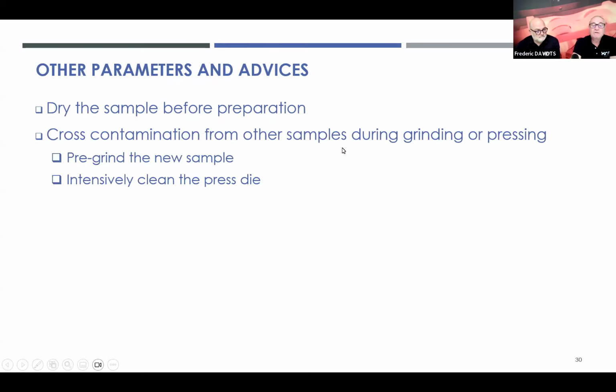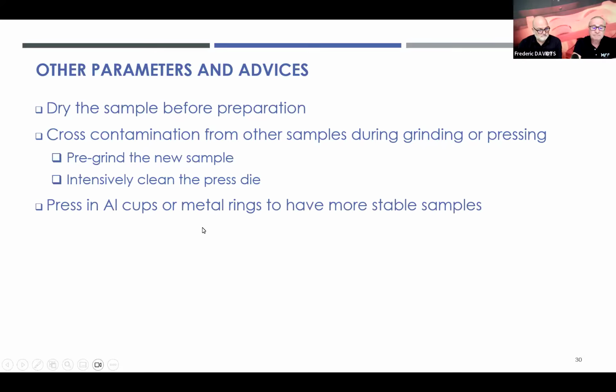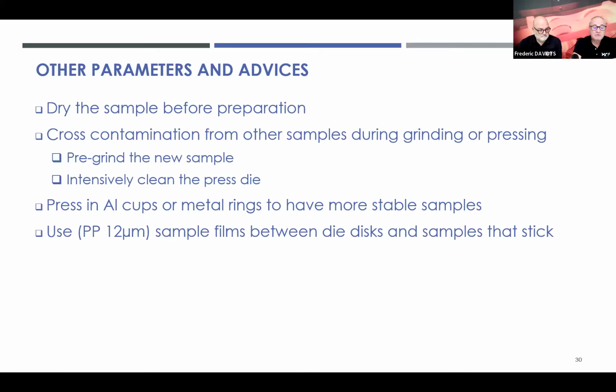Cross-contamination, avoid this, especially during the grinding and the pressing process. Eventually, pre-grind the new sample in your mill before you grind the sample that you will use for analysis, and always intensively clean the press die. You can also use aluminum cups to have more stable samples. They will keep the edges of the sample better together.